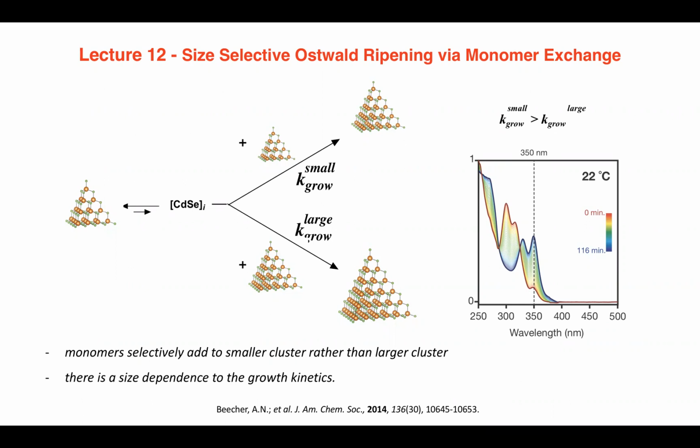So this is another very clear example of smaller crystallites consuming solutes faster than large ones in an Ostwald ripening experiment. So no nucleation at all. In fact, this is a solution of particles where small ones consume solute faster than large ones do.